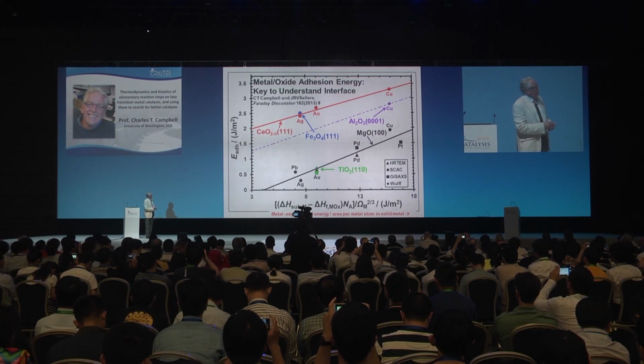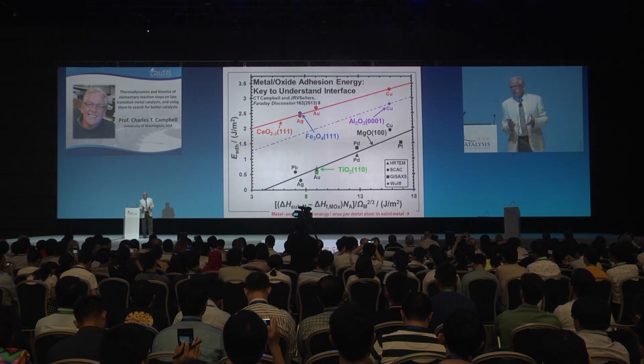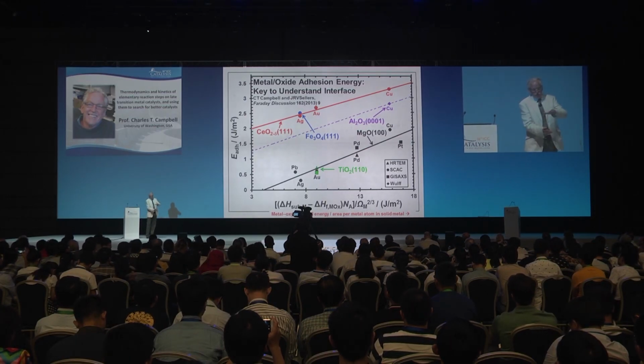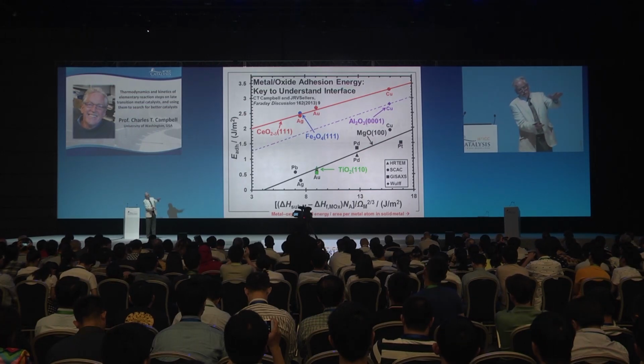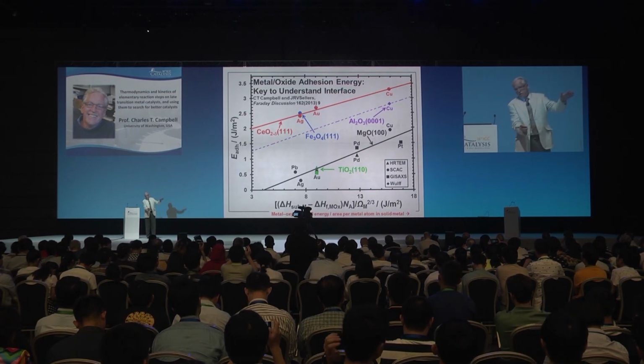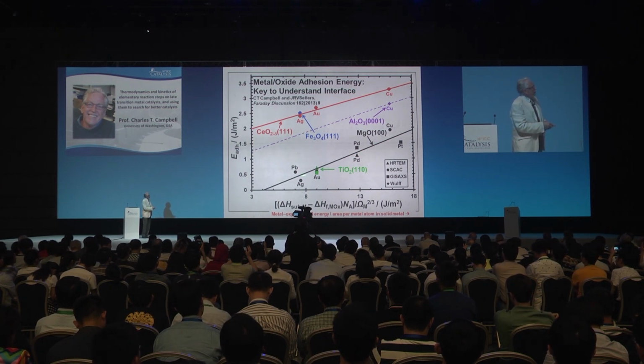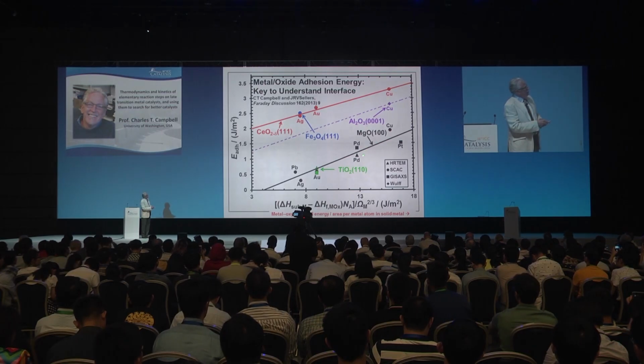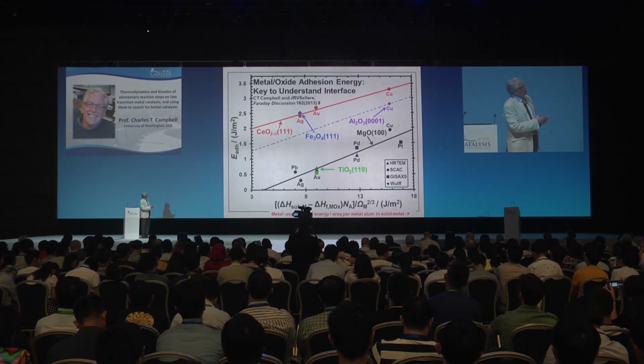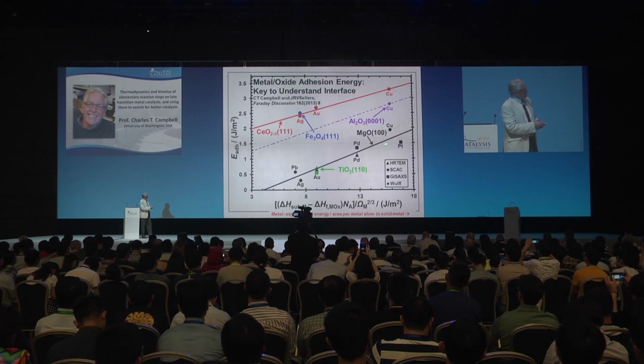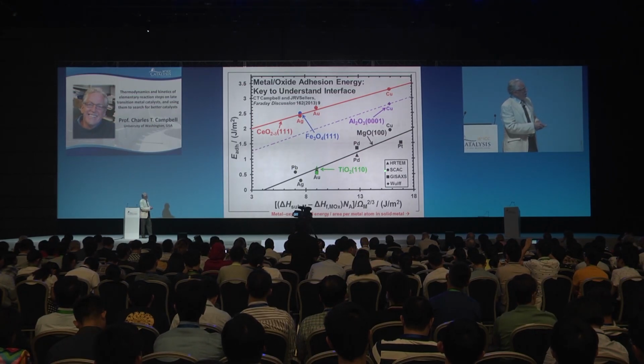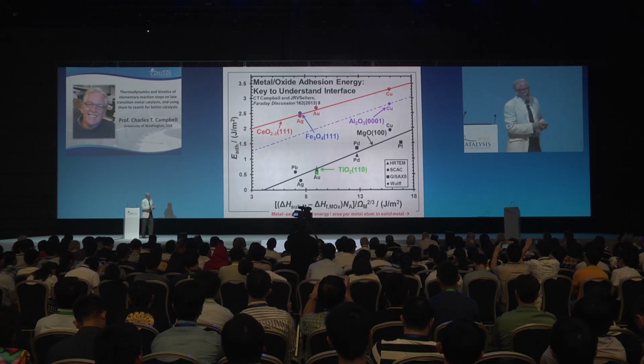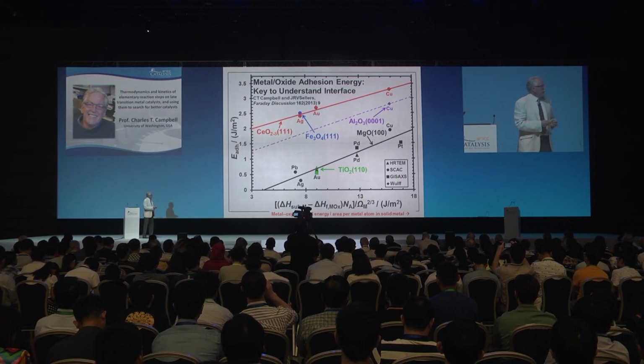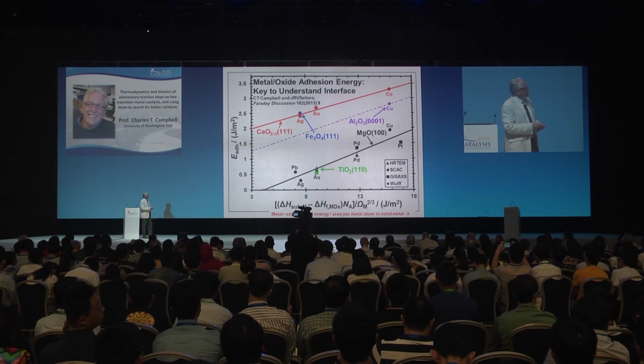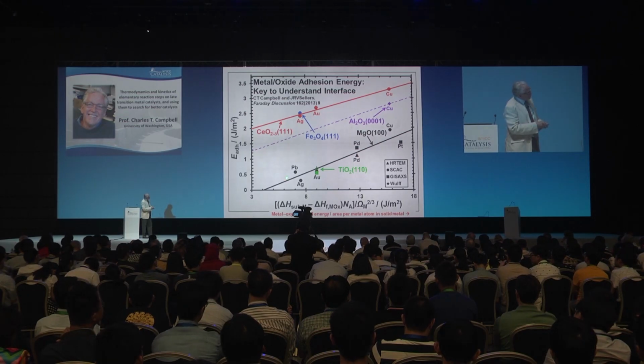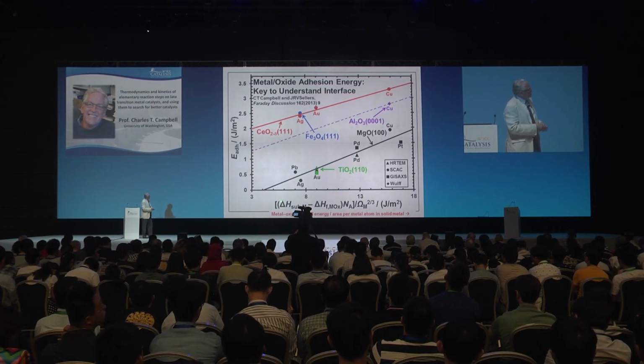And so we've been extracting the adhesion energy from our calorimetric measurements. Adhesion energy is, by definition, the energy it takes to separate the cluster off of the oxide support, if you like. And these data in black points here for magnesium oxide have already been published in 2013. They come from not just our calorimetric measurements, but also from analysis of the particle shape using electron microscopy or X-ray scattering measurements.